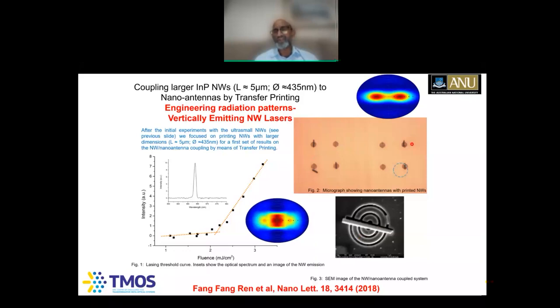You can see the close-up of this one. They're able to precisely locate these ones very nicely. Then you do not have any nano antenna. And then what you get is a light emission from both ends of the nanowire, which I've shown you earlier, because the nanowire acts like a Fabry-Perot cavity. But once you really put this nano antenna, light gets engineered towards a vertical direction, and you suddenly start getting vertical emitting nanowire lasers.